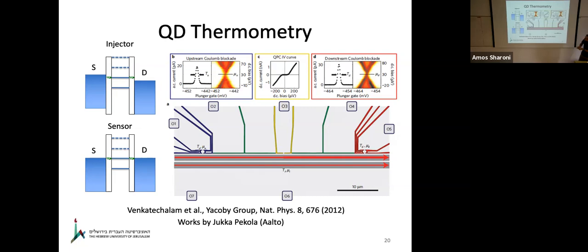But a dot is not only a spectrometer, it can also be a thermometer, because if everything is good and everything is quiet and everything is stable, transport through the dot is dominated by the thermal smearing of the source and the drain. And therefore you actually measure the temperature. This is work by the group of Amir Yacoby, where he measures the temperature of quantum Hall edges and uses these quantum dots defined by gates within the 2D gallium arsenide as thermometers for heat flow within the quantum Hall edges.